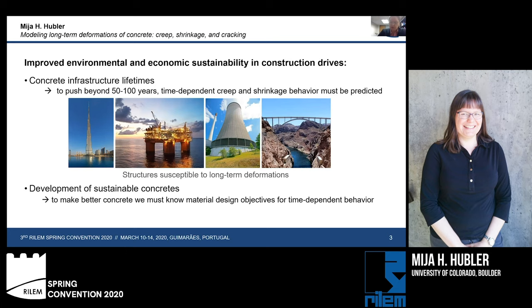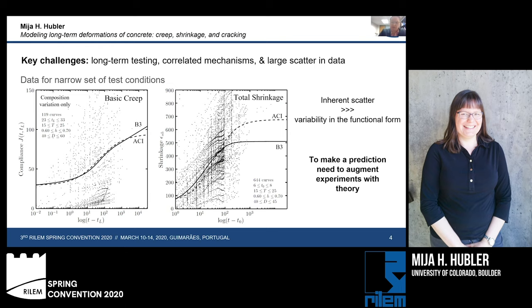The key challenge to developing long-term predictions for creep and shrinkage of concrete is that we can't really do 100 years of testing. Long-term testing right now is usually around however long a graduate student might be part of a research group. So that's about 3 or 4 years. And so we need to extrapolate from those data in order to push the lifetimes of concrete and new concretes that are developed. The second challenge is that there are many correlated mechanisms that impact creep and shrinkage, not just moisture movement as well as the mechanical loading. And these all have an integrated role in our prediction.